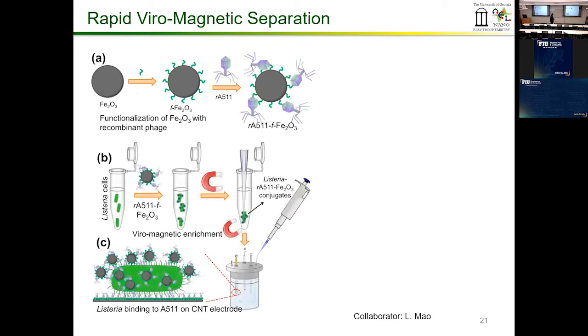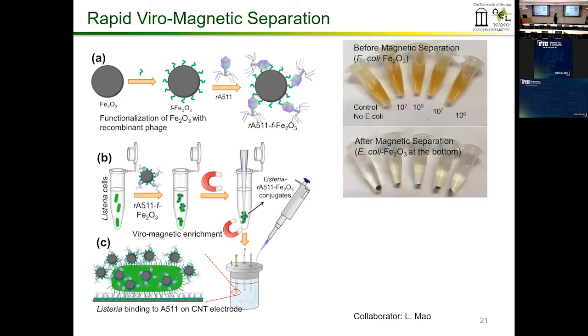So let's say you have a sample containing bacterial cells. You introduce these virus-modified magnetic particles into the sample. They're going to attach to those bacteria because the virus attaches to the bacteria. Now you can pull it with a magnet, and you're basically going from 1 ml to maybe 0.1 ml here. So that way you're concentrating the sample, and you can do multi-stage concentration steps. Then you can introduce it into your electrode to achieve the detection. So that's exactly what we tried.